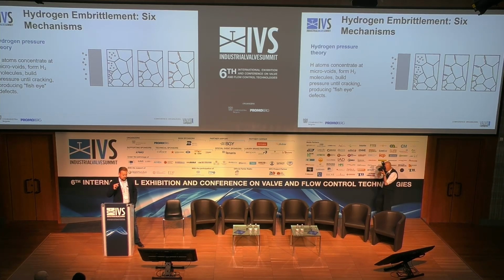So basically what happens is that hydrogen bonds on top of the metal and splits into two active hydrogen atoms, which penetrate inside the metal. They start to concentrate, as you can see in the image, on the small cracklings that are naturally inside the metal, and they start to merge. So you have what are called fish eye defects, which actually cause the failure of the metal after several applications, because the keyword is that this mechanism occurs after several applications. The more you use your metal, the more you use the high and low pressure, the pressurization mechanism, the more you accentuate this phenomenon. So this is the oldest one, the less elegant one.